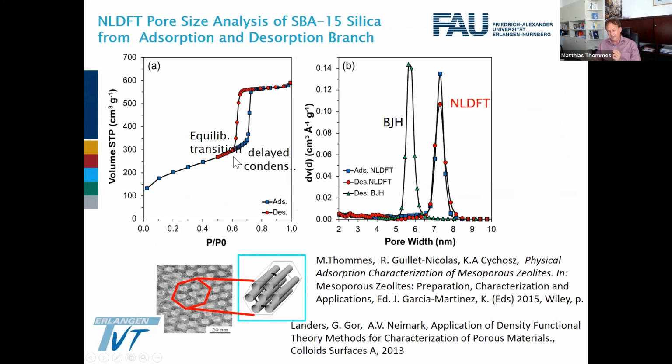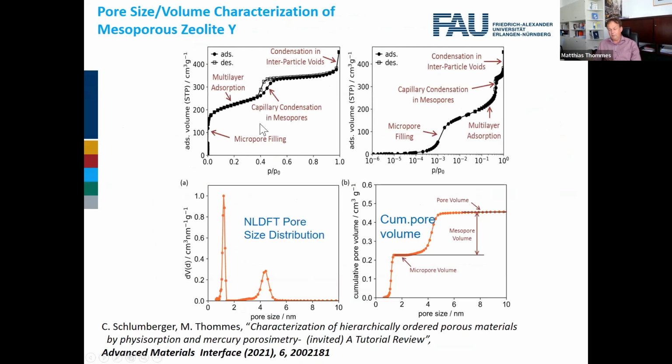And in this case, you can analyze both the adsorption and desorption branches for the pore size analysis, because this advanced DFT approach allows one to take quantitatively into account, for a given pore size and geometry, the delay in condensation due to these nucleation barriers, which we discussed before in my talk. So you have a beautiful toolset which you can apply to obtain reliable pore size information from adsorption when you look at more complex systems, like this one.